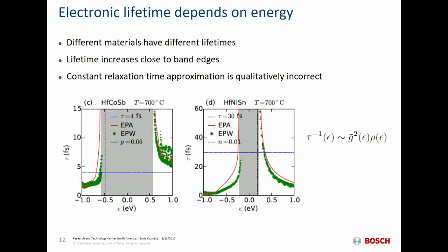And also in practice, people usually assume the value for this tau to be something typical of a semiconductor, something on the order of a femtosecond. It's actually also not a constant as a function of material composition. So for instance, here, the best fitted tau is about an order of magnitude different from the best fitted tau in this material. And these are two different compositions here. So we don't capture the energy dependence or the composition dependence, which is a problem.